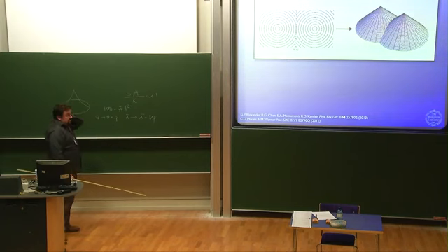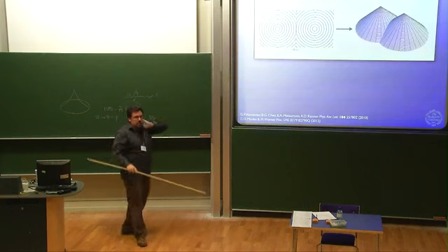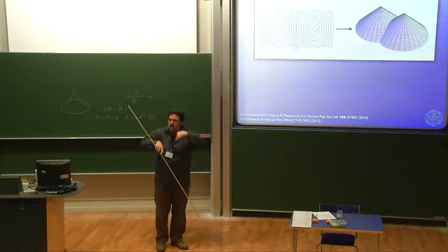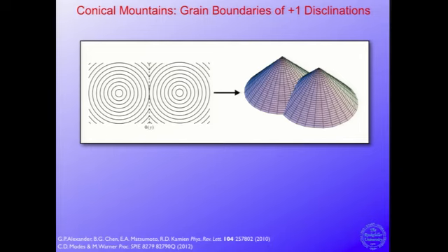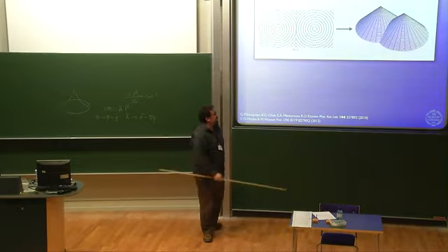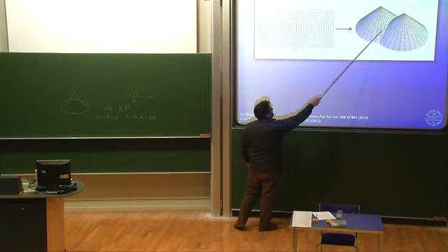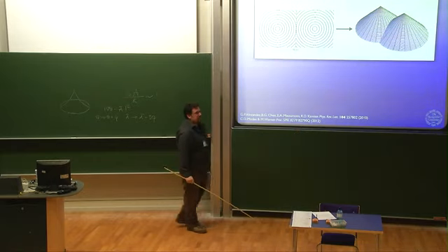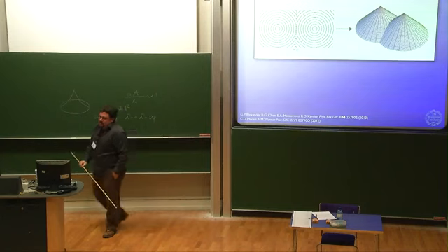So, more curvature effects. I mentioned a moment ago that when you had two cones meeting one another, they gave you some line of distributed Gaussian curvature. If you actually want to have that, you can seed that in. And it's very simple. You just write down two different +1s. You let them meet at some line. And you look at the line, and you see that the restriction of the angles meeting, the directors meeting at the same angle, is satisfied, but now there's a spatial variation to the angle of meeting. And that gives rise to this sort of mountain pass geometry,